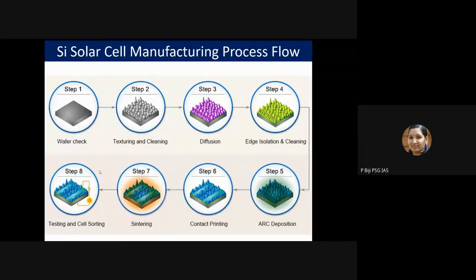Then the next important process is contact printing, because we have constructed the solar cell now. What we need is for the current to be collected from this photoelectric effect. So the metallization happens through silver screen printing. The most commonly used technology is silver screen printing. After printing the silver paste in appropriate dimensions, depending on the design, sintering happens. During sintering, it makes contact with the emitter layer, and further the cell testing and cell sorting happen.